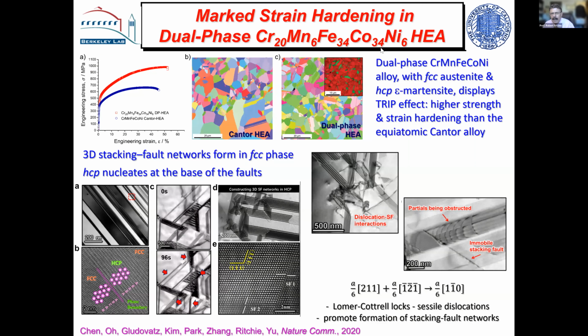Now, there's some different types of materials here. This is a dual phase version, slightly different than the original Cantor alloy composition. Again, a very, very simple microstructure, but some of the grains are hexagonal. And when you deform this one, you get even higher strength. This is the dual phase. This is the Cantor, the original one. You get higher strength and higher strain hardening.